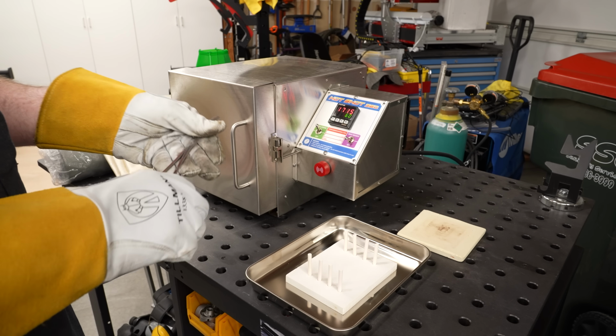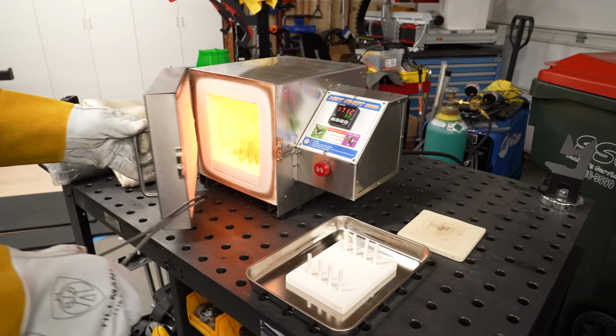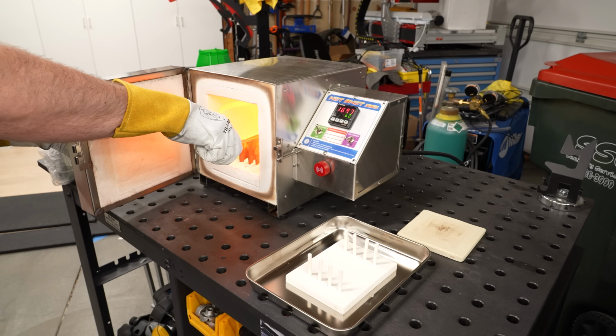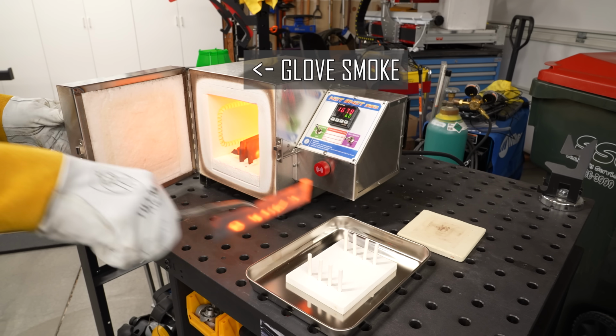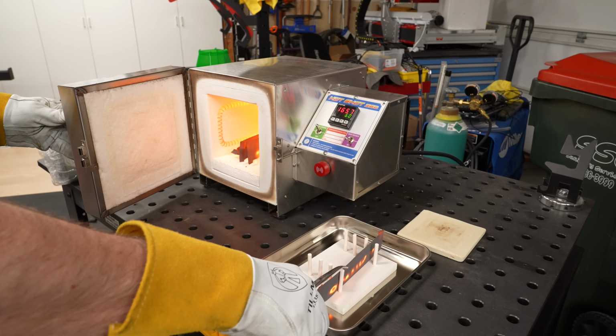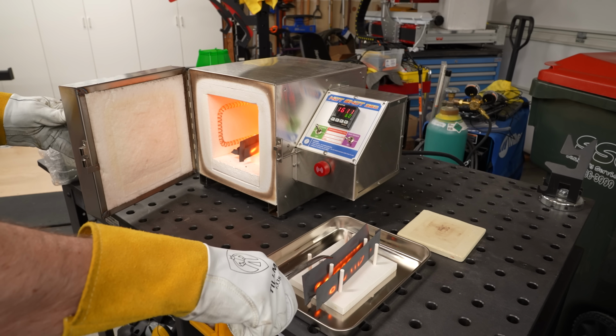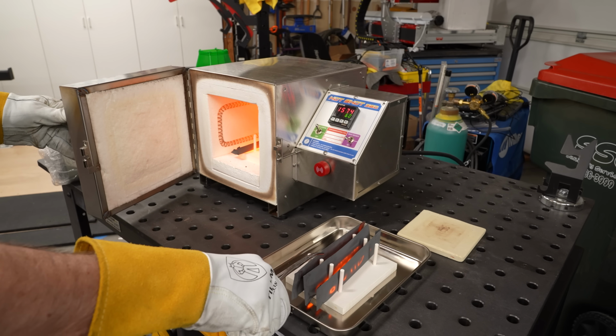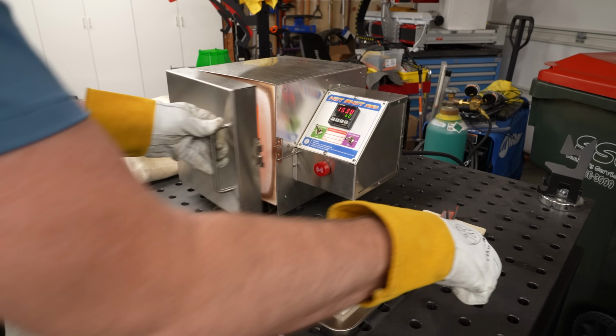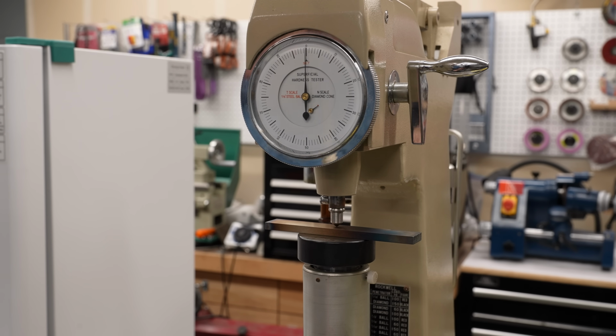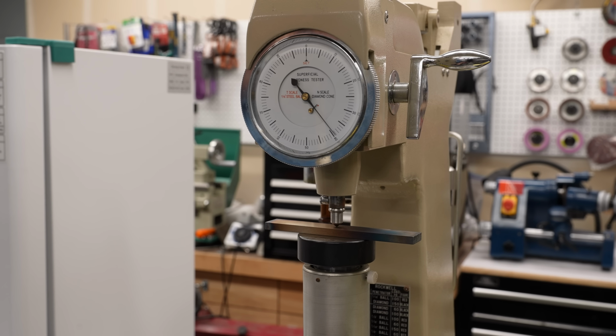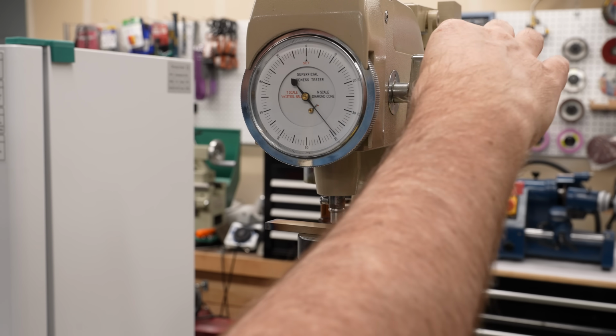The total cycle is about 5 hours, and then the parts come out of the oven and onto another ceramic rack to cool. A2 tool steel is air quenched, and for thin sections like this, cooling in the foil packet works just fine. It's also way easier and safer than trying to open the hot foil packets. After cooling to room temperature, the test sample measures around 61 Rockwell C, so the heat treatment worked.